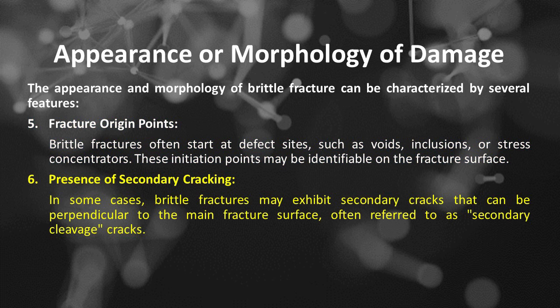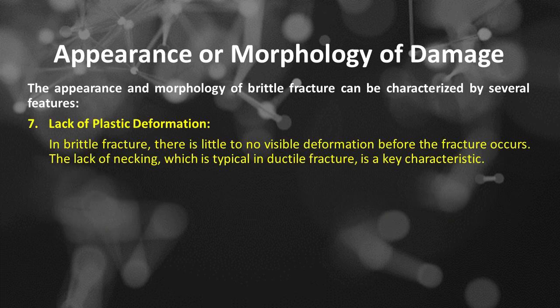Number 6 is presence of secondary cracking. In some cases, brittle fractures may exhibit secondary cracks that can be perpendicular to the main fracture surface, often referred to as secondary cleavage cracks. Number 7 is lack of plastic deformation. In brittle fracture, there is little to no visible deformation before the fracture occurs. The lack of necking, which is typical in ductile fracture, is a key characteristic.